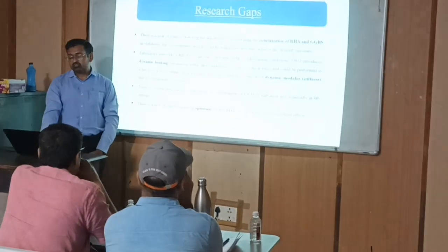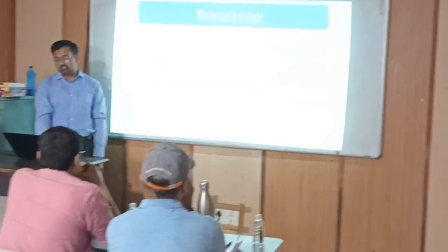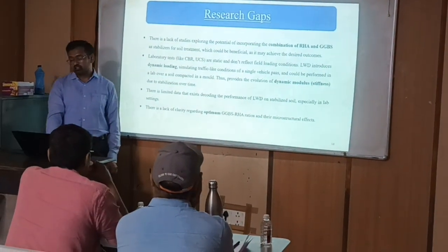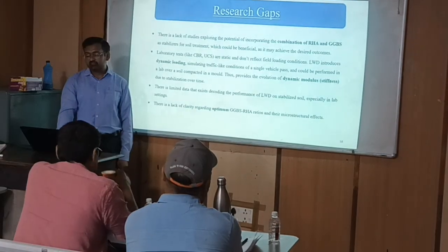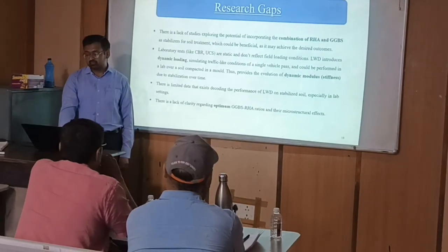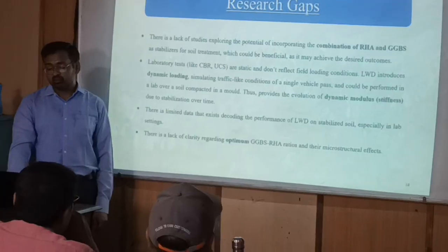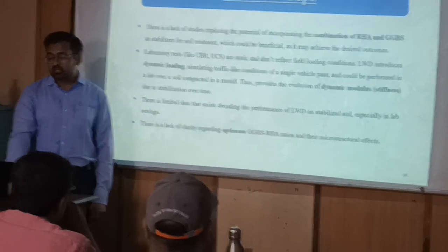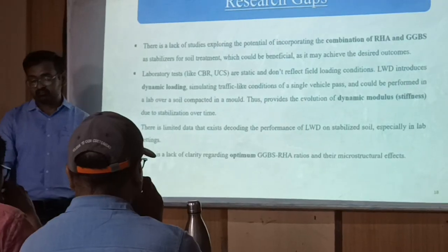For soil treatment, which could be beneficial as it may achieve the desired outcome. Laboratory tests like CBR and UCS are static and don't reflect field loading conditions. The lightweight deflectometer introduces dynamic loading, simulating traffic-like conditions of a single vehicle pass, and could be performed in a lab over a soil compacted in a mold. This provides the evaluation of dynamic modulus.